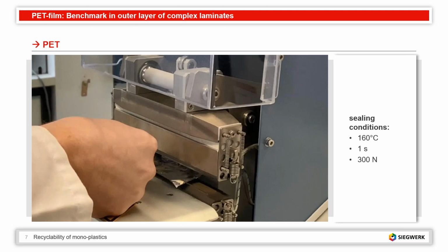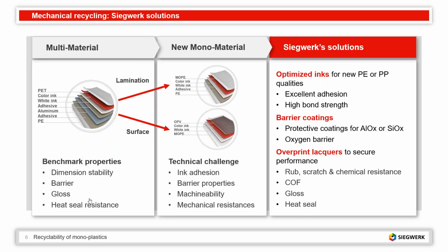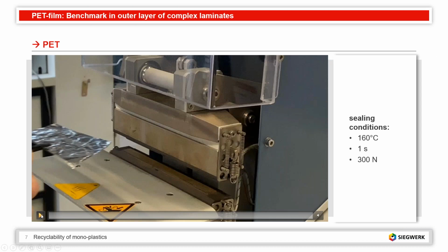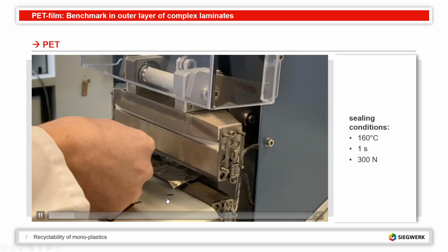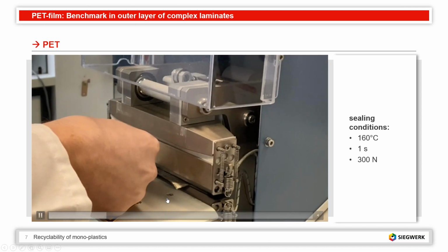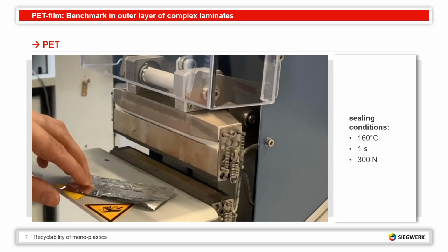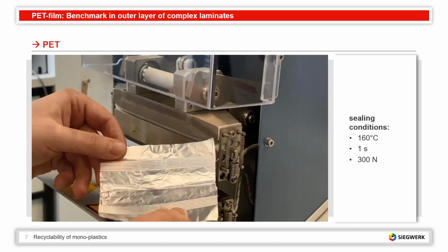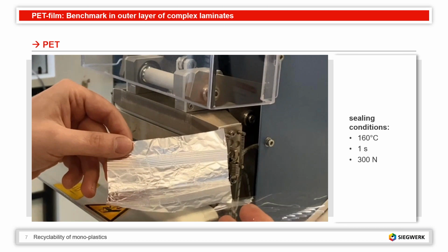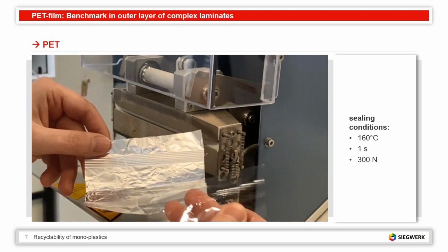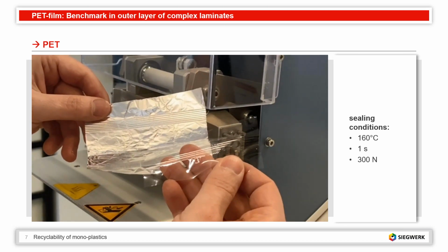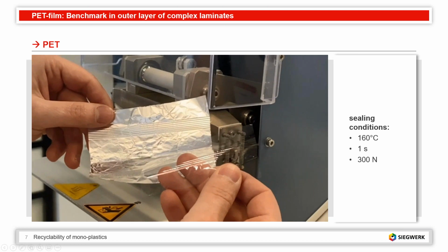And oops, sorry. Now it works. And the sealing condition is 160 degree, 1 second, 300 Newton. And you can see the employee opens the aluminum film and takes out the PET film, no problem. And this is not surprising, because 160 degrees is not very challenging as a sealing condition for PET.